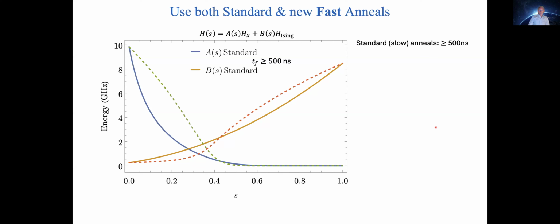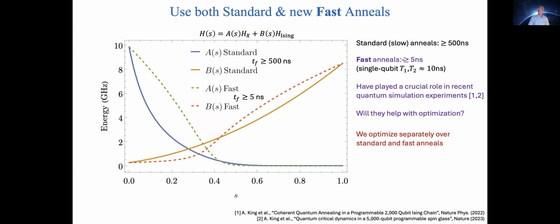Okay, and then finally, and this is new for those of you who may have heard versions of this talk before, we have been able to use fast anneals as well. So the standard anneals are the solid annealing schedules shown here. The minimum anneal time is 500 nanoseconds or 0.5 microseconds. But with the fast anneals, the minimum anneal time is 5 nanoseconds, which is important and significant because the single qubit T1 and T2 are estimated to be around 10 nanoseconds. So we can firmly get into the coherent annealing regime, which was indeed used to great success by Andrew King and company in a couple of recent papers on quantum simulation, where they demonstrated coherent quantum annealing.